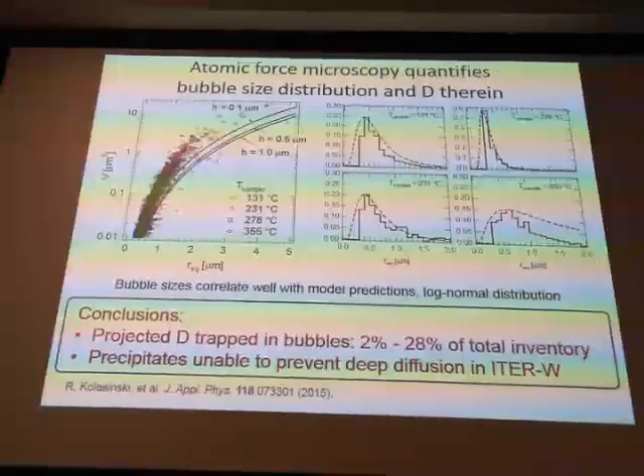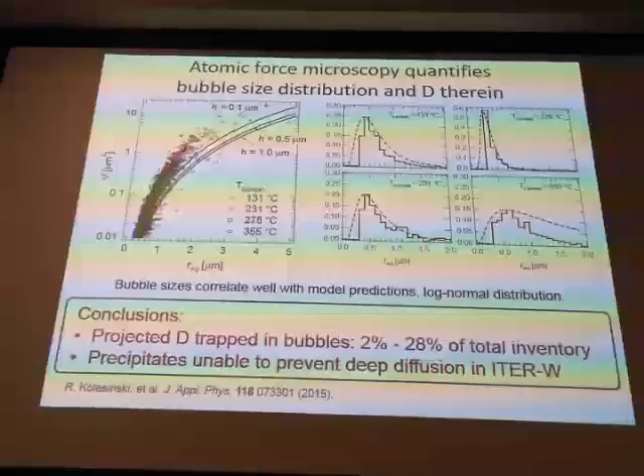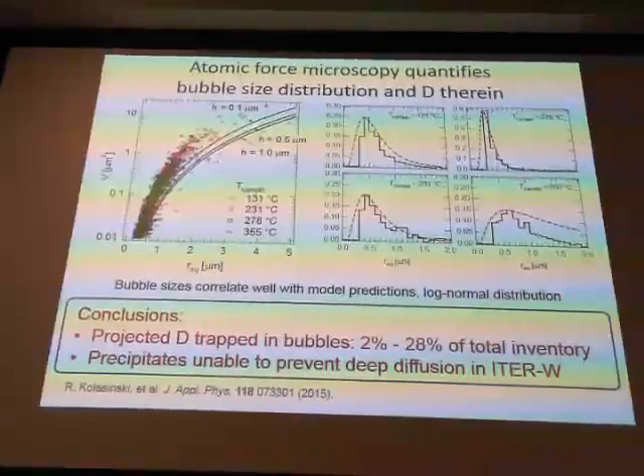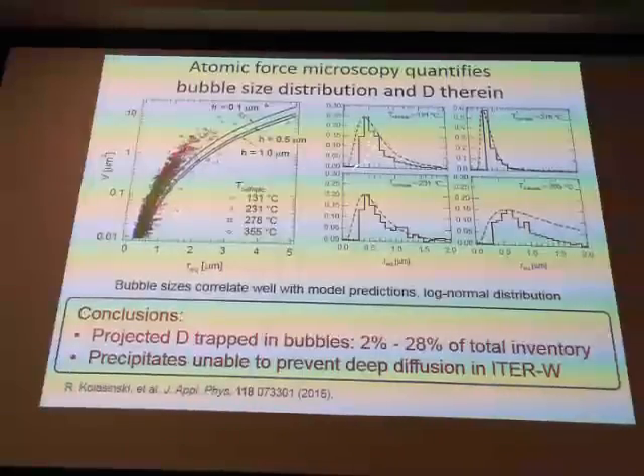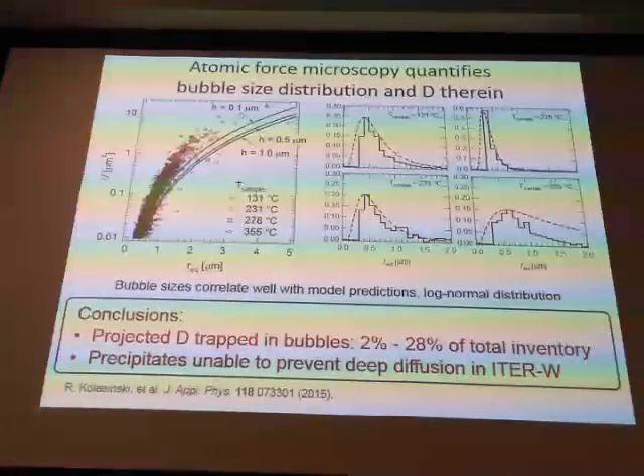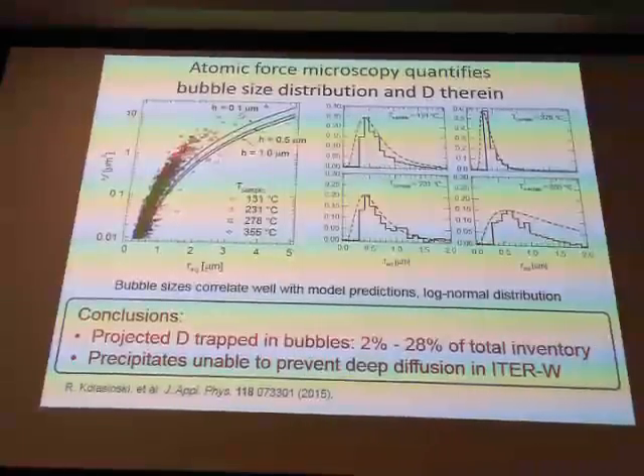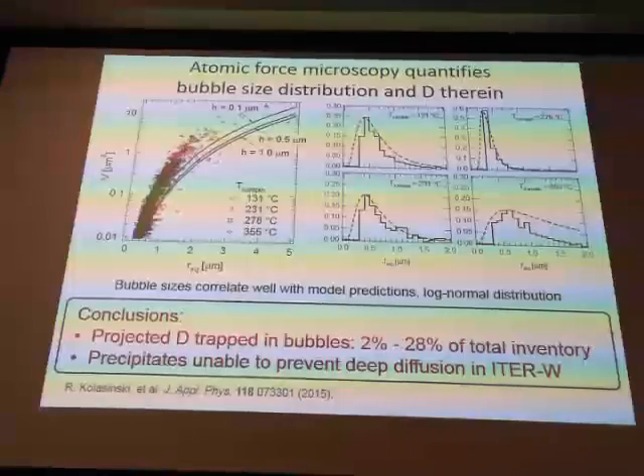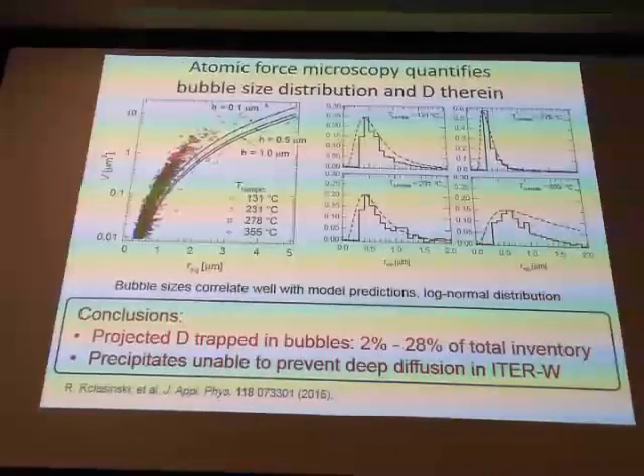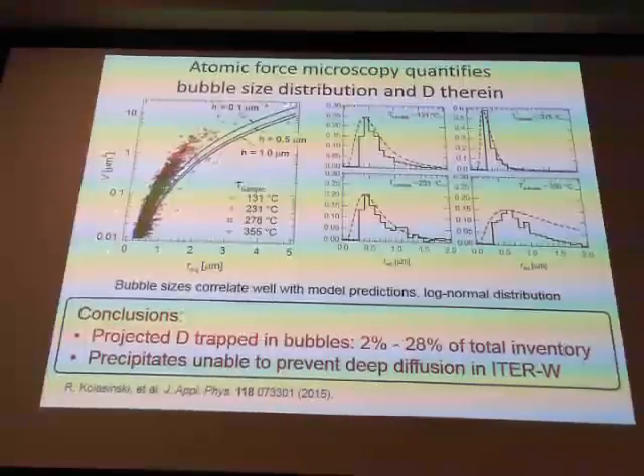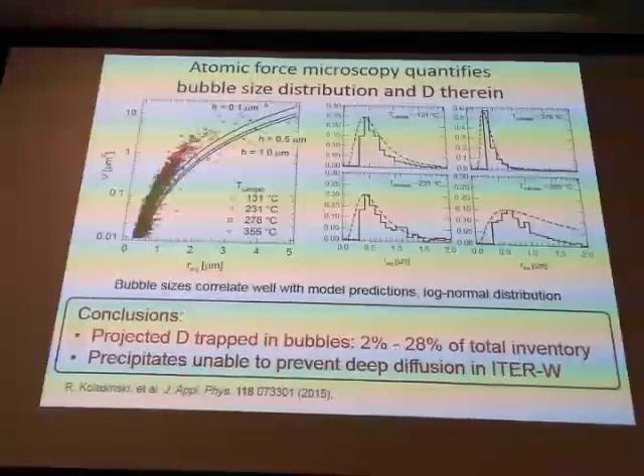And so based on this, we were able to develop a relatively straightforward model for the bubble size distribution. We measured the surface perforations here as a result of these bubbles in AFM, and did a statistical analysis. We found that they basically conform to a log normal distribution, which is about what you'd expect for a material that requires a source-dependent growth phenomenon. And then the bubble size distribution corresponded reasonably well to this model that we had developed for a thin layer delaminating from the surface and then being pressurized by internal gas.